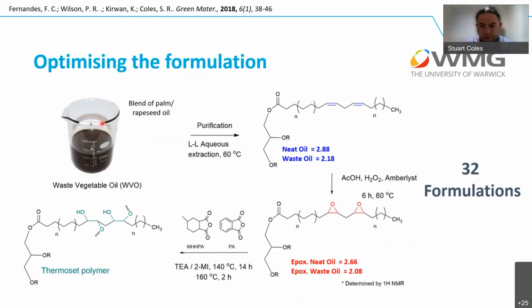And so here, again, we did our blend of palm oil and rapeseed oil, and after it had come out of the cooking, we purified it with a little bit of aqueous extraction and characterized the number of double bonds, just to know exactly how many we had. The difference there between the neat oil and the waste oil was about 0.7 of a double bond equivalent. So we lost quite a bit of chemical functionality, but there's still quite a lot on average per triglyceride unit, well over two double bonds. So there's still enough reactivity there to do something with.